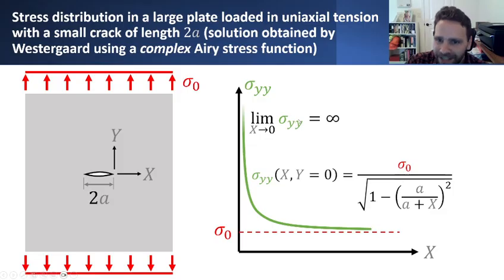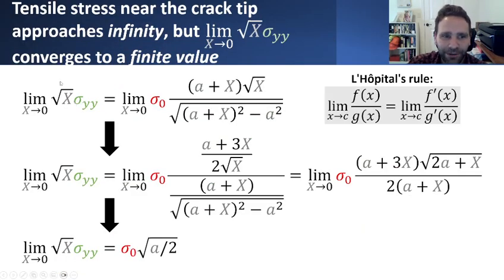Nonetheless, while the stress might zoom off to infinity, it's interesting to note that if we were to look not at sigma yy in the limit as x goes to zero, but instead at something slightly different, a quantity that involves sigma yy times the square root of x. We can make some substitutions, and maybe even apply classical L'Hopital's rule to this expression to manipulate it a little and simplify it even further. After making these adjustments, we notice that this term, the square root of x times sigma yy, does converge to a finite value, in contrast to sigma yy itself in the limit as x goes to zero.